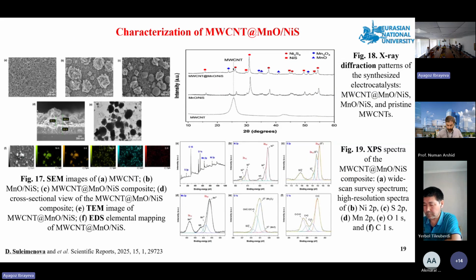For this slide, we can see the characterization of the ternary composite. SEM images show that multiwalled carbon nanotubes form a porous network, with spherical manganese oxide particles and cubic flower-like nickel sulfide structures on the FTO surface. The film is uniform with a thickness of approximately 622 nanometers, showing good coating quality. EDS confirms that all components are evenly distributed, forming a well-integrated composite. XRD and XPS results confirm the successful formation of manganese oxide nickel sulfide on multiwalled carbon nanotubes, which improves electrochemical performance.